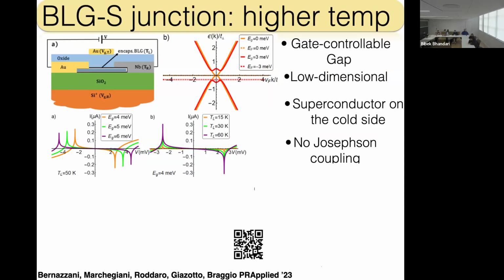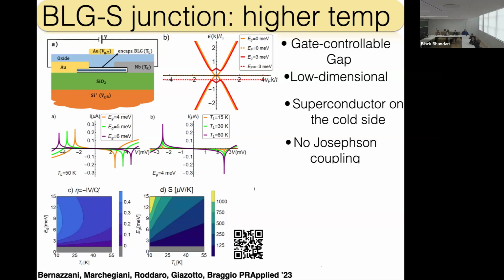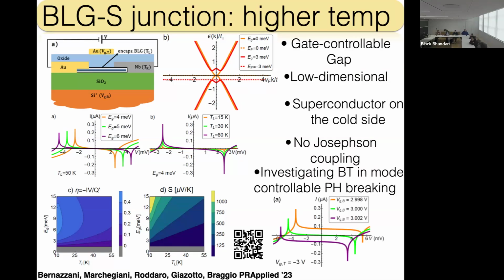And in this case, if you make the computation for this type of system, it's very similar, and you get this type of IV curve where you see you still have the bipolar thermoelectric effect. So this demonstrates that you don't need two superconductors, but only one. And it tells you also the strength. The effect is quite strong because it could be on the order of 1,000 microvolt per Kelvin.